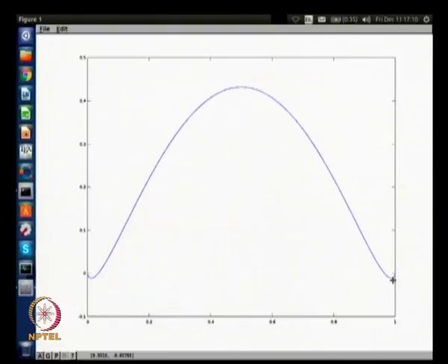That is because the entropy is calculated using the configurational argument. The configurational argument says that I replace some B atoms or A atoms by the other type. If I have, say, pure A or pure B, which is what these two extremes correspond to, and if I take very small number of atoms of other type, suppose I take pure A and then I have pure A, there is only one configuration, but the moment I introduced one B atom into this pure A, then if there are some n number of sites, then there are n different configurations. So, that much will be the increase in entropy.